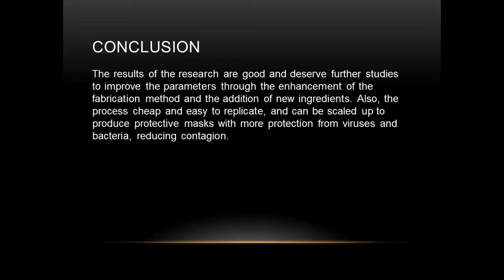So the conclusion we came to is that the results of the present research are promising and deserve further studies to improve the process parameters through changes in solution concentration, use of native cyclodextrins and surfactants, and improvement of time and temperature to obtain uniform particle size, to avoid particle agglomeration and allow better distribution of the particles all over the TNT fibers. Also, the process is low cost, easy to do, and can be scaled up to produce disposable protective masks with extra and safe protection from pathogenic microorganisms.